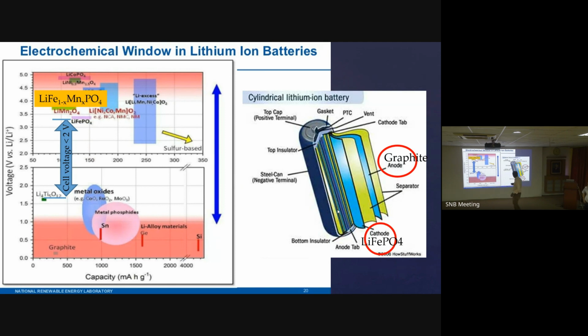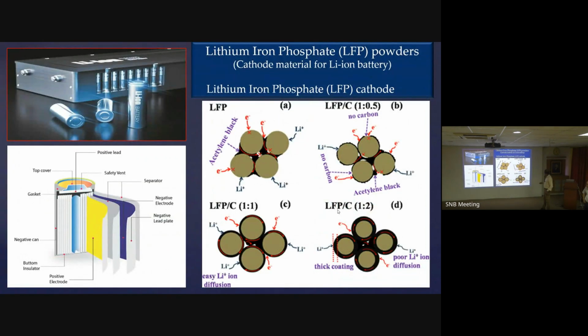Maybe I didn't get it very well because you showed this coating of the carbon. This coating was on the cathode, which has no role; actually it is detrimental. But you need to have carbon to collect the current because the conducting element is not conducting. If you have more carbon, then that's a waste. So you should have a bare minimum carbon, a balance with good conductivity. That's what we optimize.